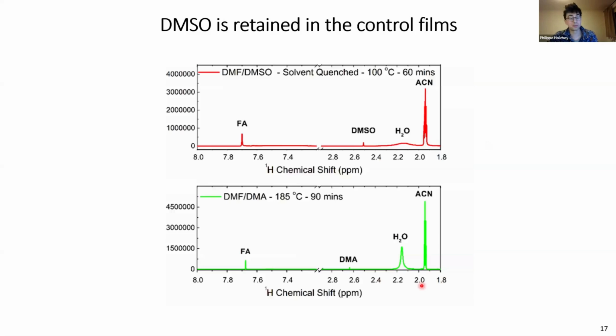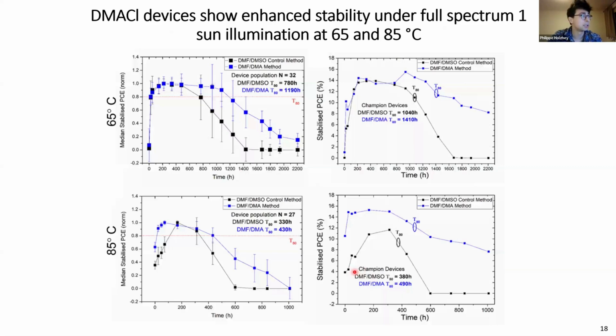Another thing is that because we left out the DMSO, so we just use DMF, we obviously don't have any DMSO left in our films. So here we have some solvent NMR. This is in deuterated acetonitrile, so that's why you see this acetonitrile peak here on the right. For the DMF-DMSO films, even after annealing at 100 degrees, we find that there's a DMSO peak and the DMF peak here. And for the DMF-DMA route, we find that there's some DMA left in it, but no DMF, at least not in the solvent NMR. We didn't find that. And those devices also show better stability.